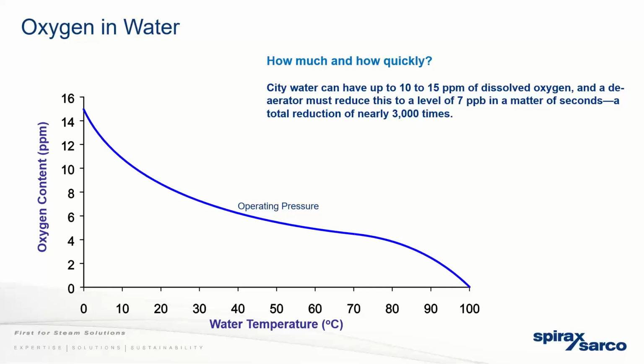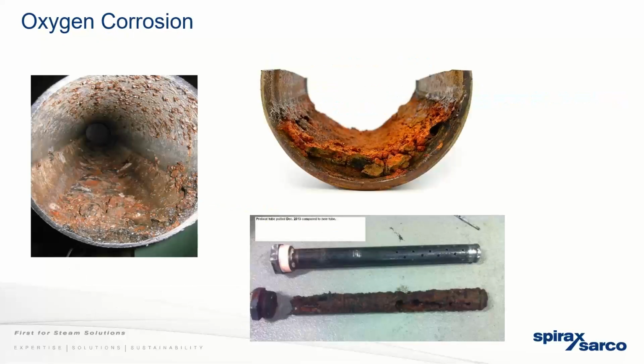As cold water comes in, it has to heat it up, remove the oxygen, and that reduction goes down to about 3,000 times of what it was in there. If you look at why it becomes important as well, if you see oxygen corrosion pictures here, it can be pretty devastating on the boiler itself. Boilers or boiler systems with very poor deaerators or very poor oxygen removing capabilities will actually have high corrosion. The tubes will corrode, or the coils will corrode depending on what sort of boiler you have, and they will have to replace, patch them up. So you're putting in a lot of maintenance into that at that point.